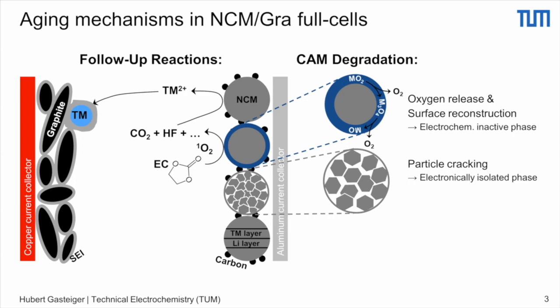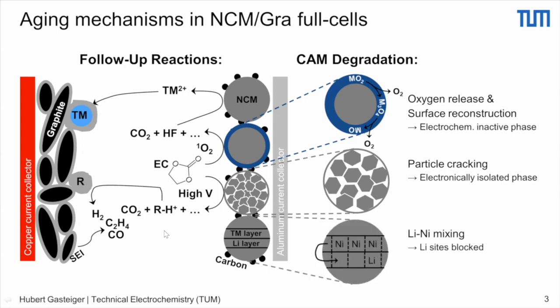The other thing we have is, depending on the cycling potential and the time of cycling, we see a cracking of polycrystalline NCM materials. So what we get is a gradual breakup of the secondary agglomerates into their primary crystallites. And that in principle can lead to electronically isolated phases in the center of the secondary agglomerates. And also, of course, at high potential, we have the oxidation of the electrolyte, which again produces protic species, which get reduced on the negative electrode, leading to hydrogen.